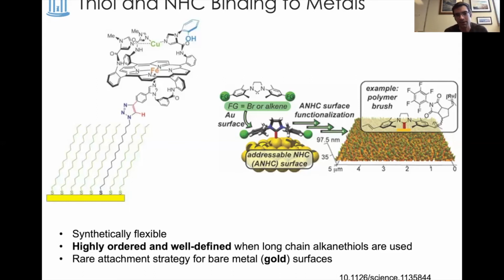And you're quite remote from the catalyst center again. And it's a relatively rare strategy that's amenable to a bare metal surface like gold, rather than metal oxides. A relatively recent development is that N-heterocyclic carbenes are also quite good anchoring groups for gold. And so these offer very different structures, different coverage patterns. And so that's been an area of recent interest in this field.